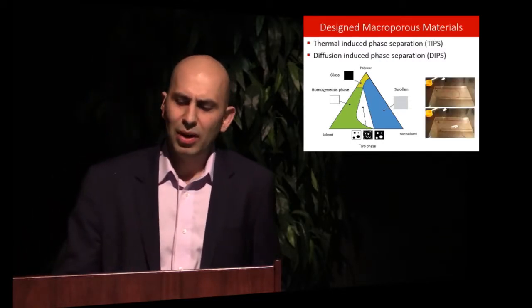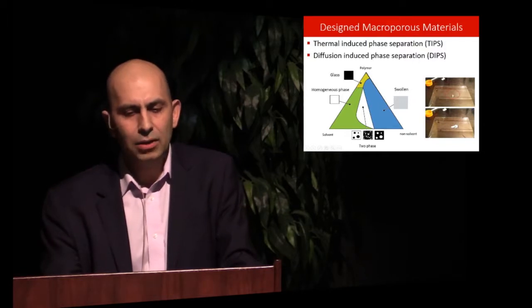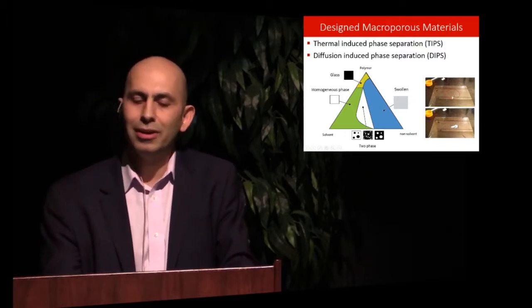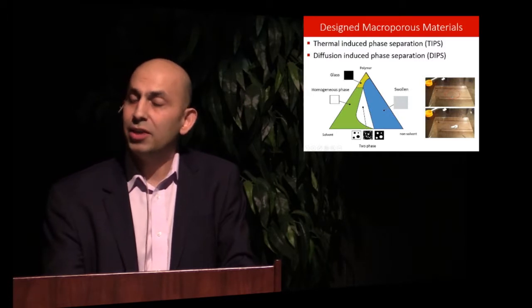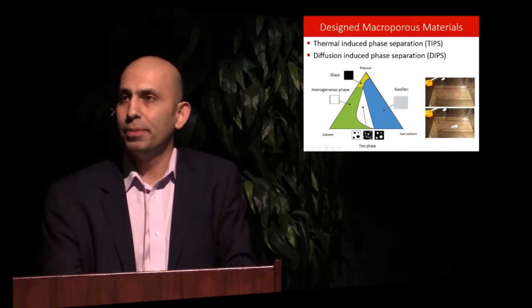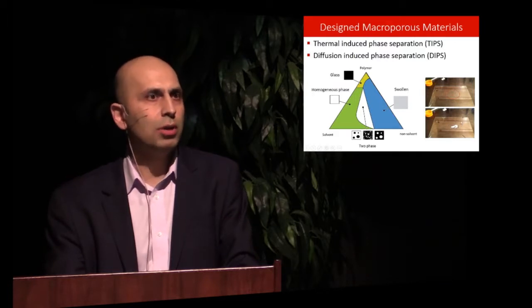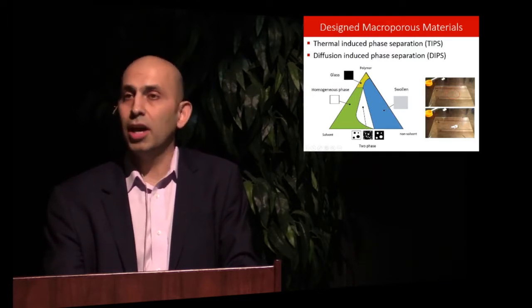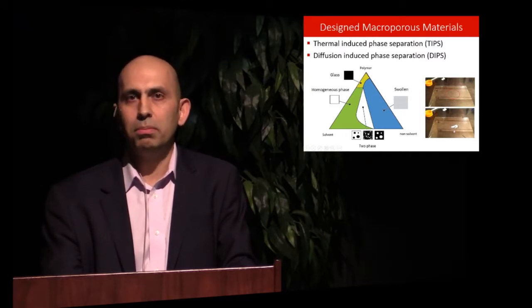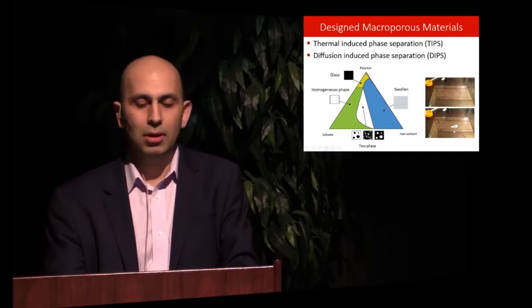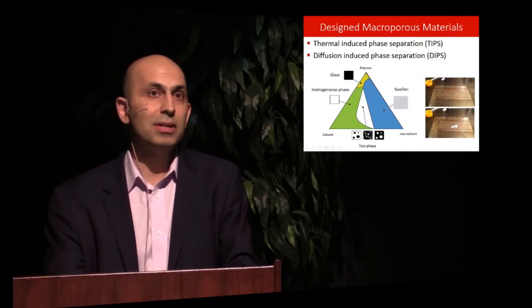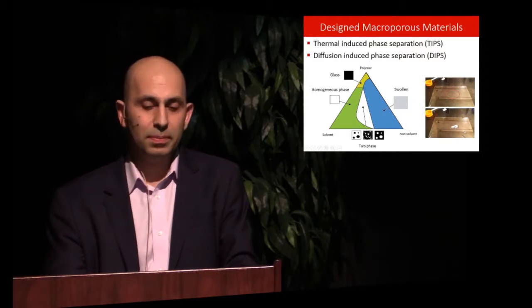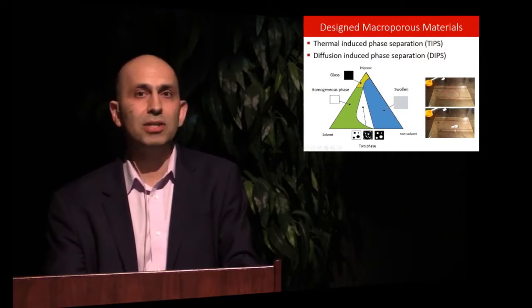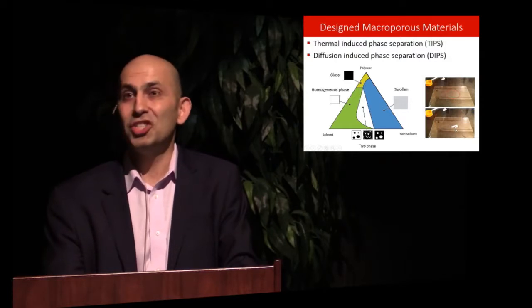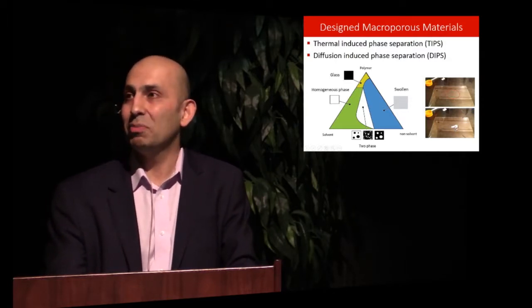Here's an example. I have a polymer solution in that little dot. That's polysulfone. Now I'm going to add a third component into that, which in this case is water. It is very similar to a salt-out process, because the polymer doesn't like water. When I adjust the conditions in this mixture, the polymer prefers to precipitate. As a result, it comes out of the solution as a solid. That's a principle that has been used for the past 30 years to make polymeric materials. It's interesting and amazing, and we do not have any replacement for that yet.